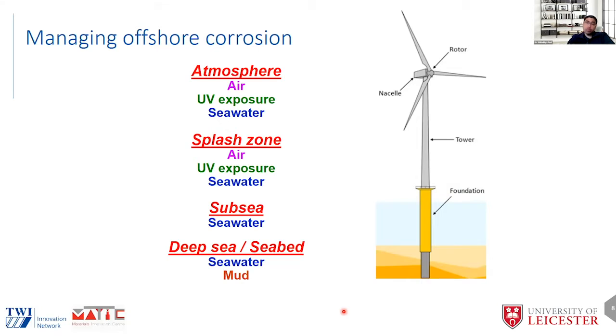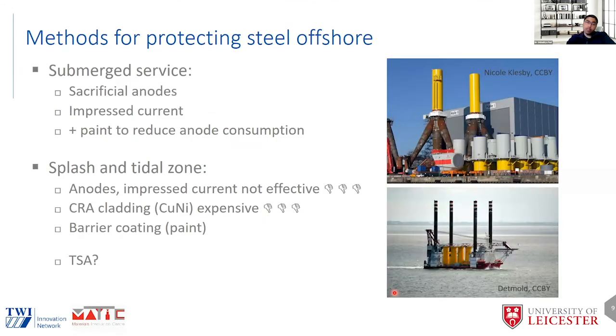So Sébastien talked about the zone where they tend to use quite a lot of these zinc aluminium with a painted layer on top, which is the atmospheric zone primarily, where you have got the rotor, nacelle, the tower. Then you've got the splash and tidal zone, where you get wetting and drying. And Sébastien also presented alternate immersion test, which is quite relevant to the tidal zone area. And then you have got the area where you have got constant seawater, where cathodic protection is fairly effective. And then you go down to the seabed and where you've got seawater and mud. So the various regions or zones within the structure may require various coating systems or corrosion mitigation methods. So I'm going to talk a little bit about some of these today.